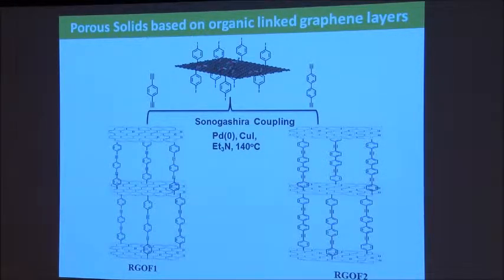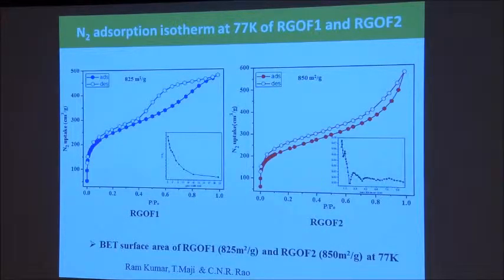Lastly, this is something I am very proud of, not yet published, just sent to a journal. You take a layer of graphene and couple it with the Sonogashira coupling reaction, making one layer coupled with different linkers. I can vary the length of the linkers, and now I can make an all-carbon porous material wherein I have linked graphene by linkers of different lengths, giving a completely new type of all-carbon porous material - all carbon porous, no metal, nothing.